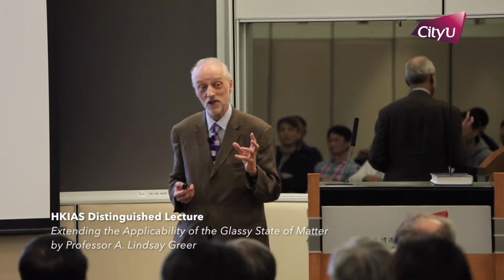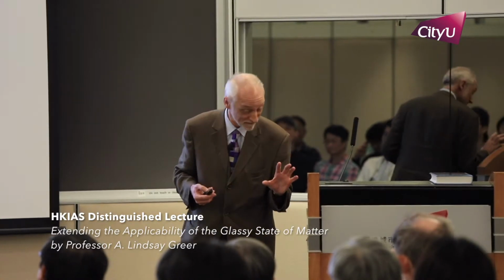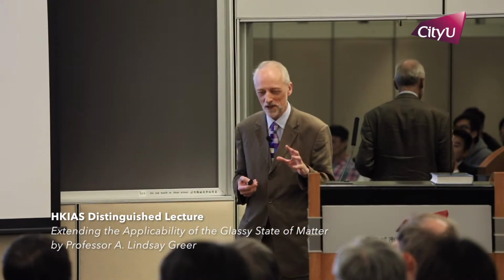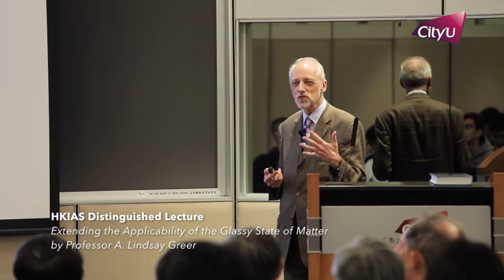I skipped past something in that slide, and indeed the general properties of the glasses. In the opening selection of pictures, one of the pictures was of golf clubs. And bulk metallic glasses have been used for the faces of golf clubs because their yield stress is so high, with a rather similar Young's modulus to the crystal, not the same, but the elastic strain limit is much higher than the crystal. So you get a much better energy transfer to the golf ball. The problem really in the marketplace was the energy transfer was too good, so they're illegal for professional competitions.